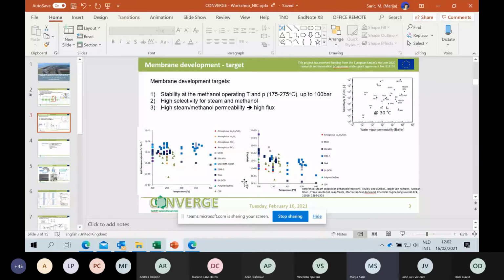To do the pre-selection of the membrane, we started with a literature study looking at the different membranes that were tested for steam separation. So what you can see in these figures are, let's say, from the literature, typically tested membranes for steam separation at these high temperatures. You can see typically that they use amorphous membranes, zeolite membranes, or polymeric membranes. And here what is really important is also steam to hydrogen selectivity. So we can see also in general trend that with the increase of temperature, the selectivity goes down. And this graph also shows some hydrogen to nitrogen selectivity for different polymeric membranes.